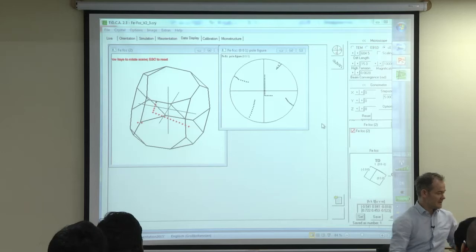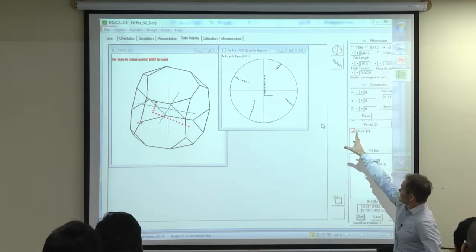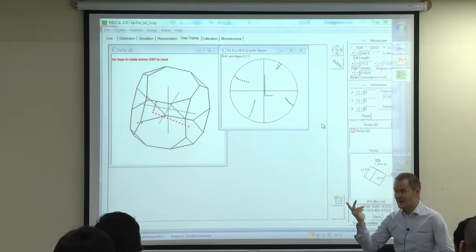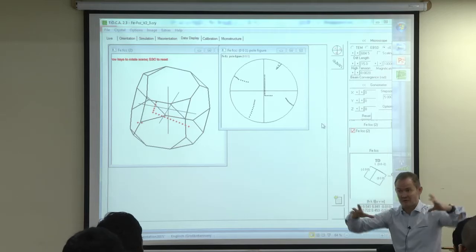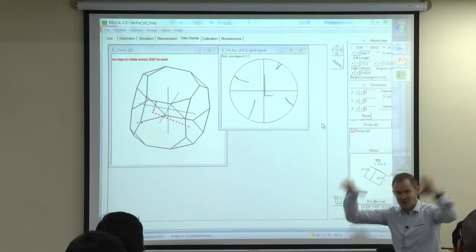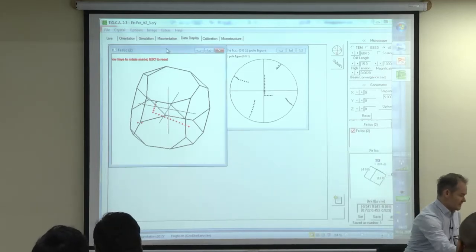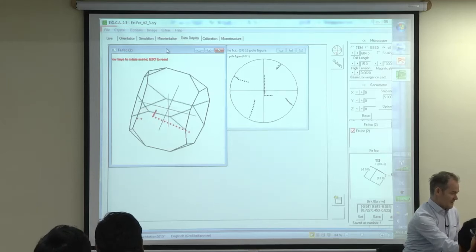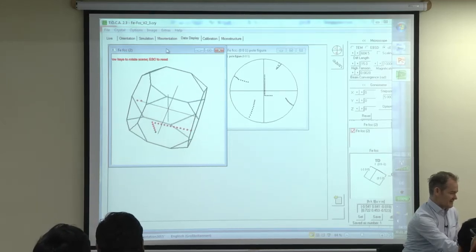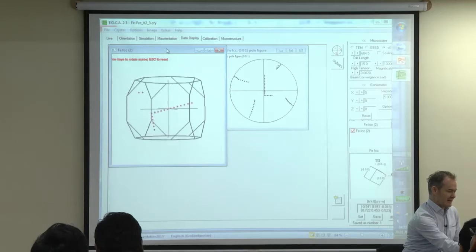So you see in the pole figures it makes a different, also not a straight line, of course not, because it's a stereographic projection. It's a spherical projection on a flat. It cannot be straight lines. But in Rodrigues space, it is really beautiful. I need to move it, otherwise you can't see it properly. It's actually a beautiful straight line.